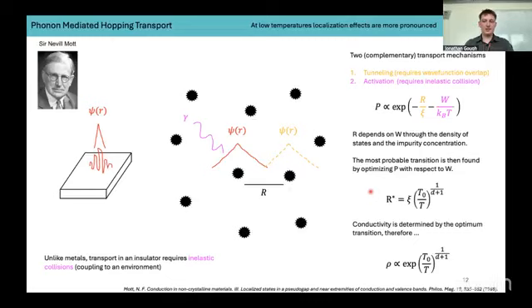This is quite surprising because you would assume that it would be easiest for an electron just to hop to neighboring sites and essentially chain up these hops until it left the system. However, you find that as the temperature decreases, the electron will hop very large distances. This is called variable range hopping. And it kind of makes sense if you think about it, even in a naive way. As your bath temperature lowers, it becomes more energy efficient to hop to a state that's very far away but close by in energy, rather than a nearby site that may be far away in energy. So that's the general explanation of why variable range hopping kicks in.